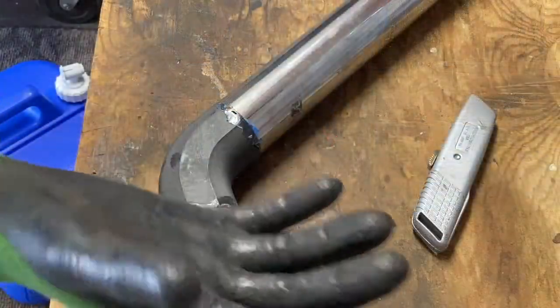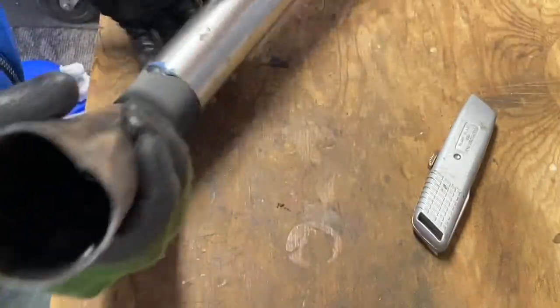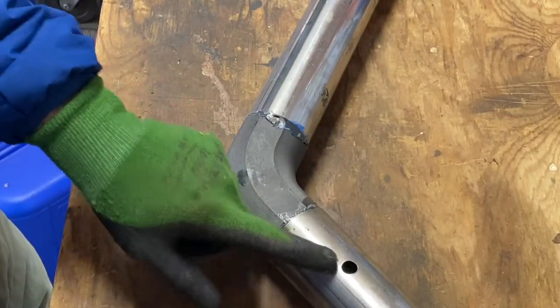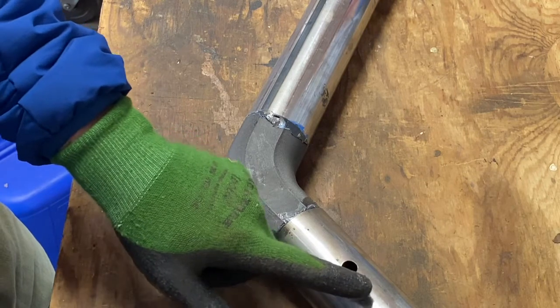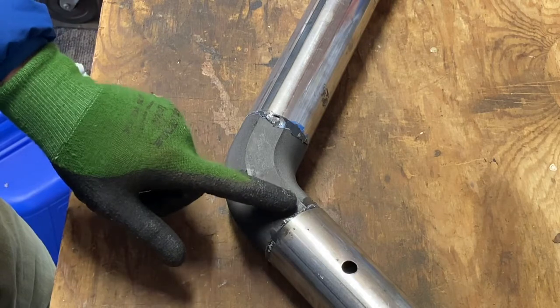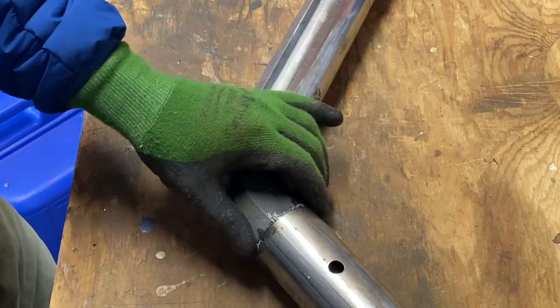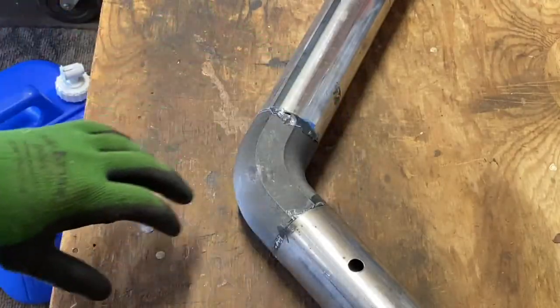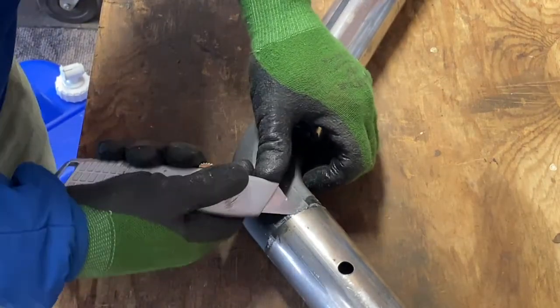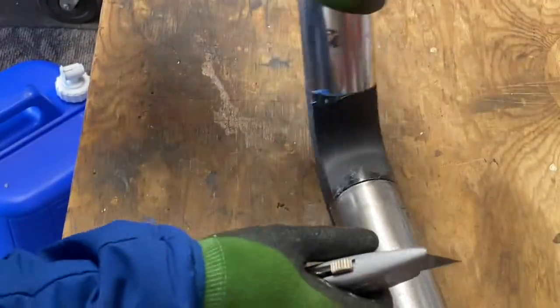So that is the epoxy — probably. Torquing on this thing in the trailer hitch of my truck, which happened to hold this thing nicely, denting and divoting the tube here. This epoxy setup wasn't totally ideal because the ID of the tube is larger than it should be for the way this lug is sized — larger than what the carbon fiber tubing is that I'm going to use. I didn't use the bond line separator, so it wasn't necessarily evenly spaced. I'm not surprised that the epoxy gave up. I'm actually impressed at how well it held up — even though it started to separate here, it's still really difficult to get it apart.